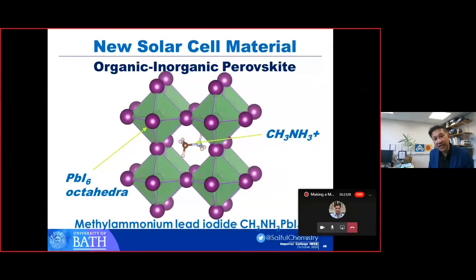The new solar cell material is based on this inorganic perovskite. It's these lead iodide octahedra. The iodide ions are in purple, and instead of a calcium ion at the center, we have this organic cation, methyl ammonium. So this is methyl ammonium lead iodide. So it has the same perovskite structure, but it's now organic-inorganic.